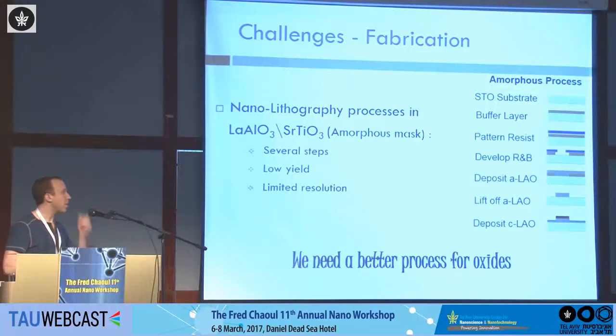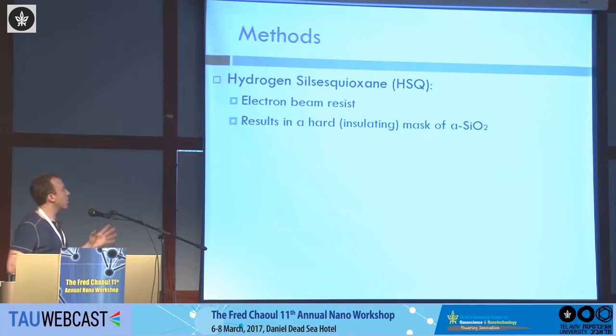So a need for a better process for oxides is required, and this is what we proposed, a new method combined with hydrogen silsesquioxane, something called HSQ. It's something that we found when we talked to Ron Koskov from the Nano Center, and actually this resist is the resist they use to demonstrate E-beam capabilities, but they don't have a lot to do with it except for those demonstrations. But for us, it's actually perfect. It results in a hard and insulating mask of amorphous silicon dioxide.